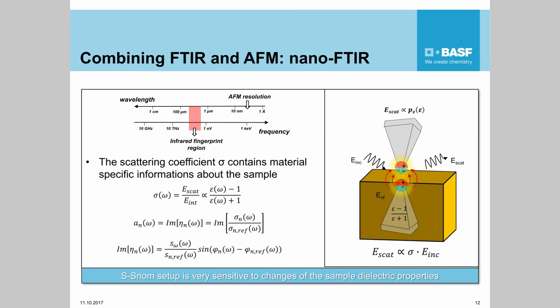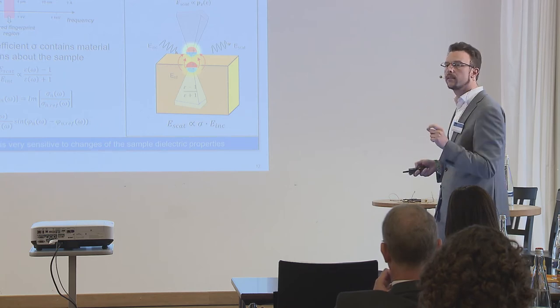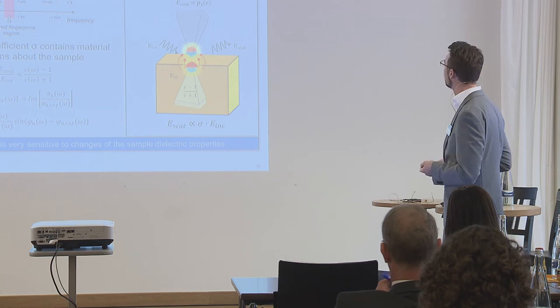When we place this tip into proximity of our surface, tip-surface interactions take place, and those interactions will change and modify the scattered light by the tip. We can relate the electric scattered field with the incoming electric field by this complex-valued scattering coefficient. Since this scattering coefficient and the fact that the electric field is highly concentrated at the tip apex, we can measure the near field signal by detector and therefore get optical properties of our sample. Using a theoretical model, we can show that this near field signal contains the local infrared absorption information of our material underneath the tip.